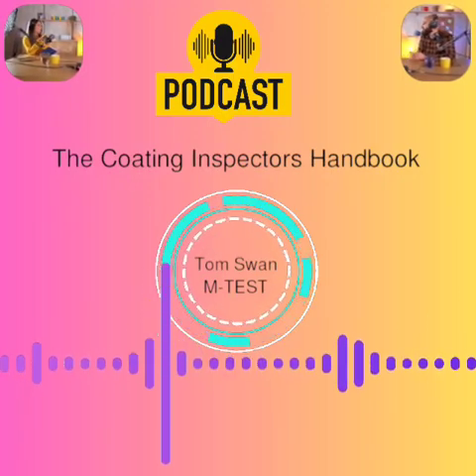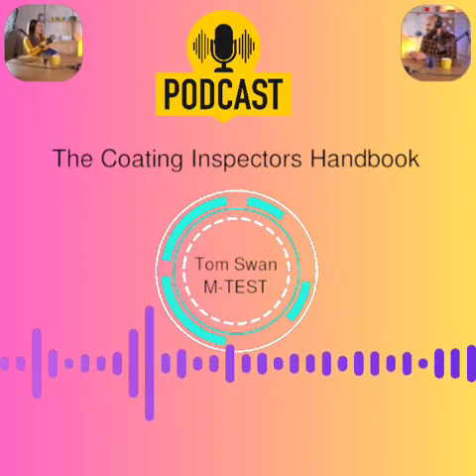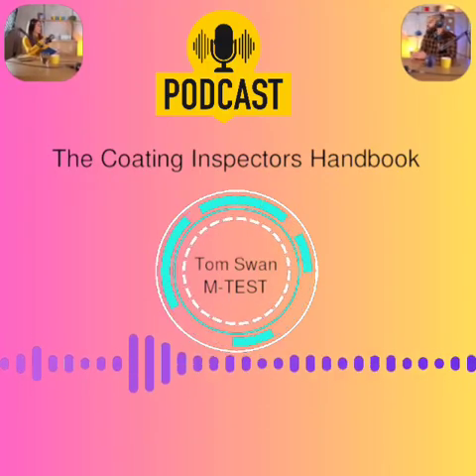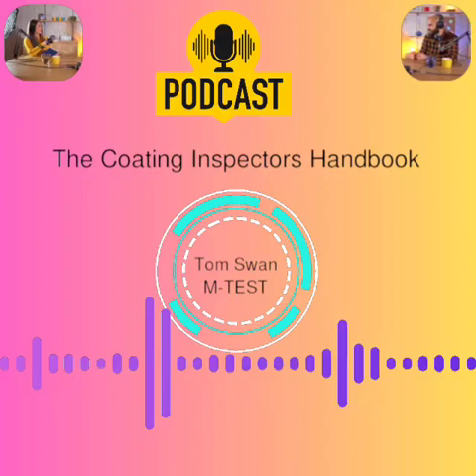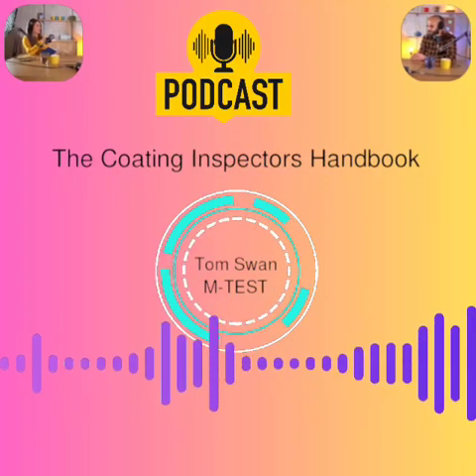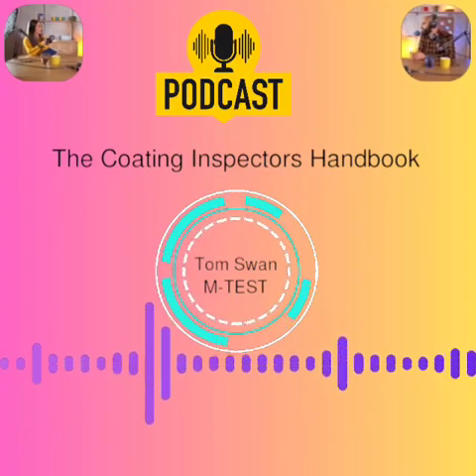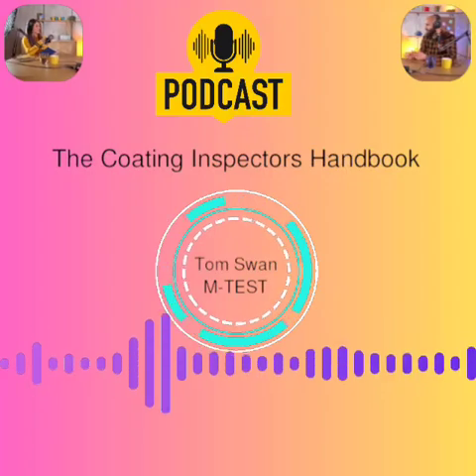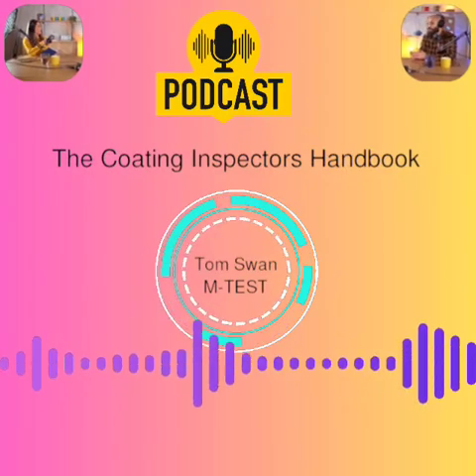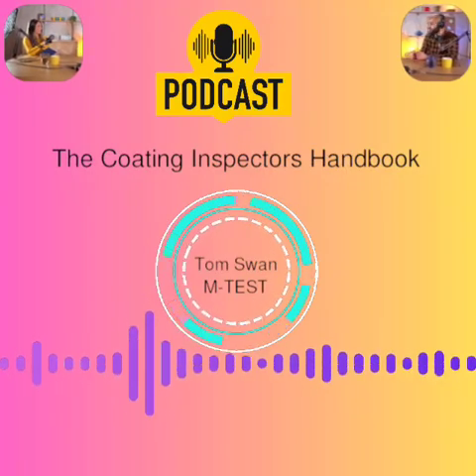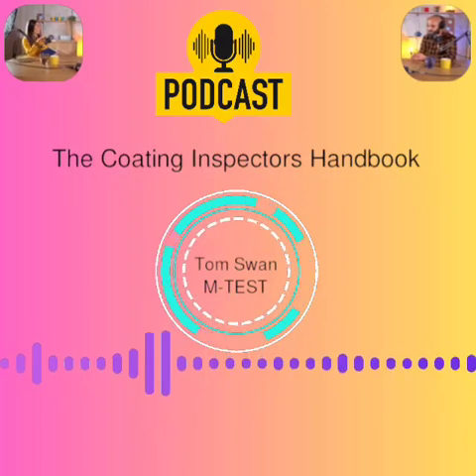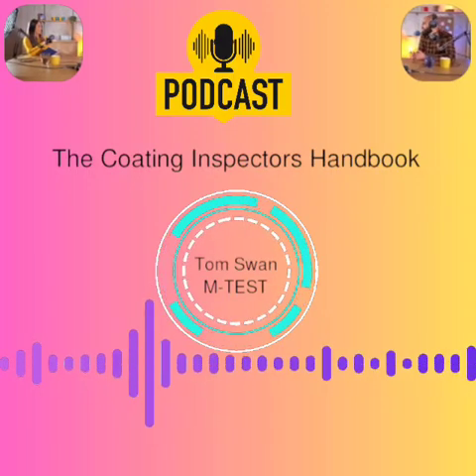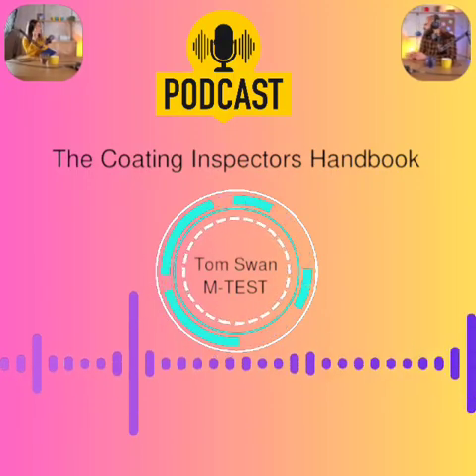And rating the test. Just the psi isn't enough. Definitely not. Record max psi and analyze the failure mode. Where did it break? Often more important than the number. Failure modes again. Adhesion between layers or paint to substrate. Cohesion within one paint layer. Glue failure, glue to paint, or glue to dolly, invalid tests for coating adhesion. Record percentages of each mode, e.g. 750 psi, 30% adhesive substrate, 40% cohesive intermediate, 30% glue failure.